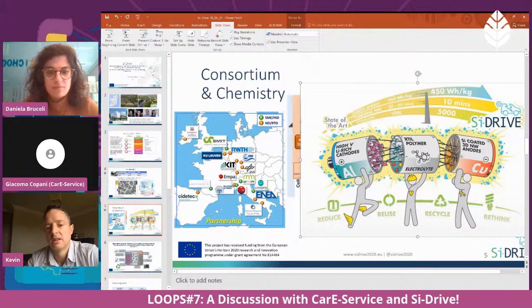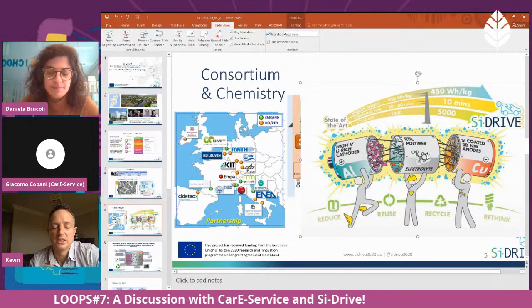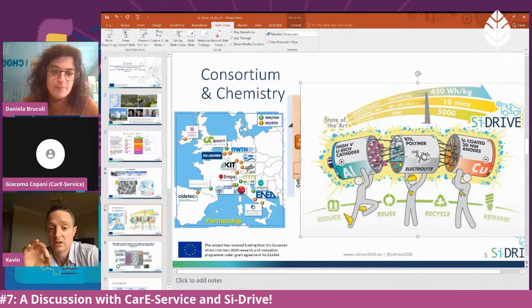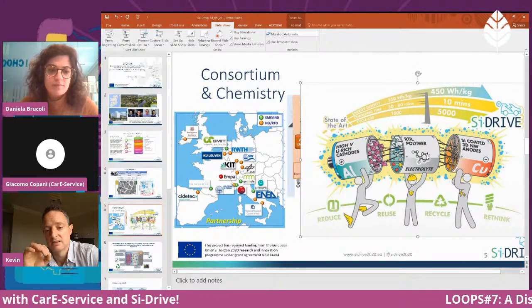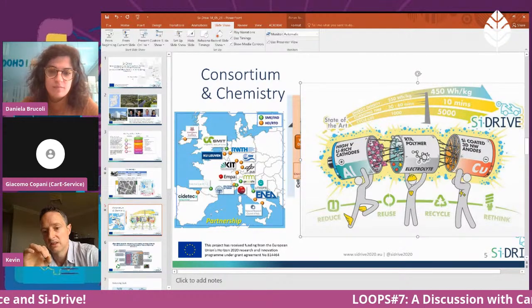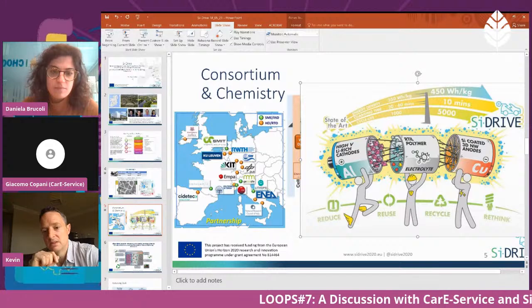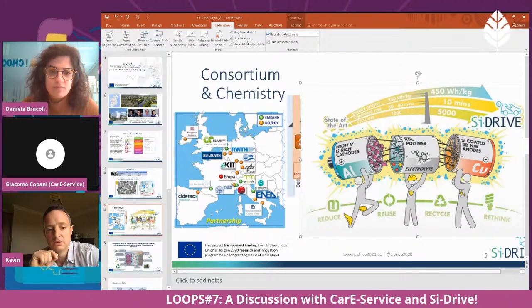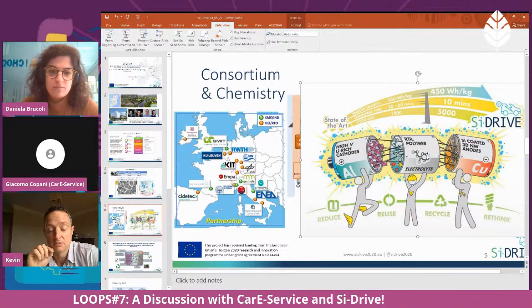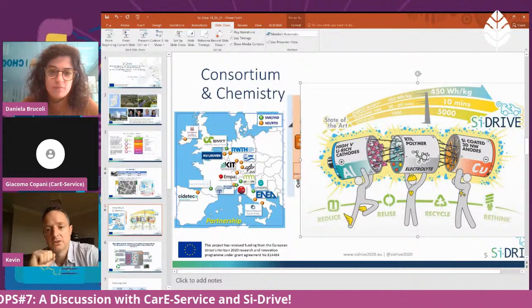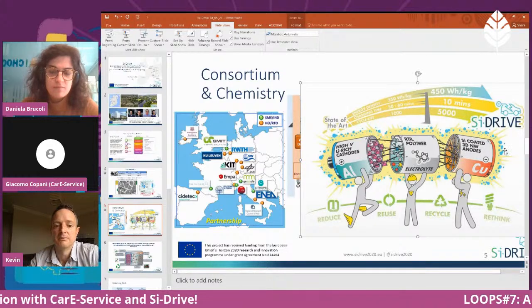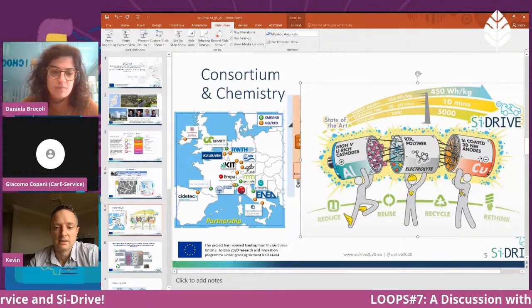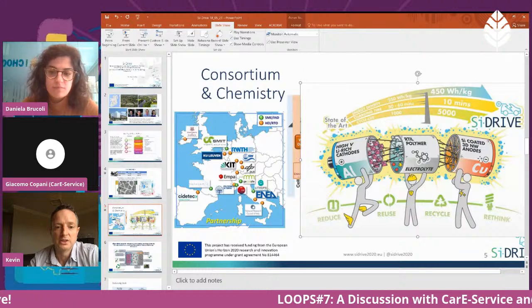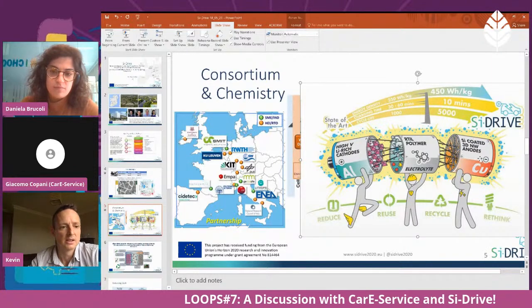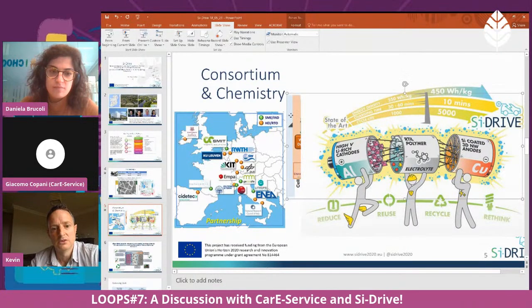And there are 2 stages in this. The first is use of an ionic liquid electrolyte, and then the second stage is a polymerized ionic liquid electrolyte, which is solid state, which will lead to an even more stable battery, or a safer battery configuration. And then at the anode side, we have silicon coated 3D nanowire anodes, and I did want to show what this